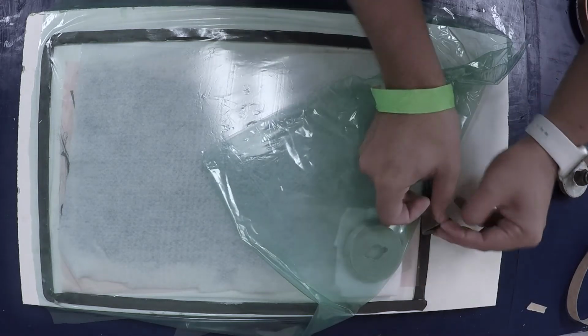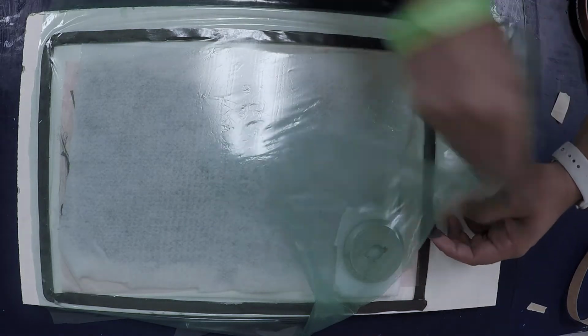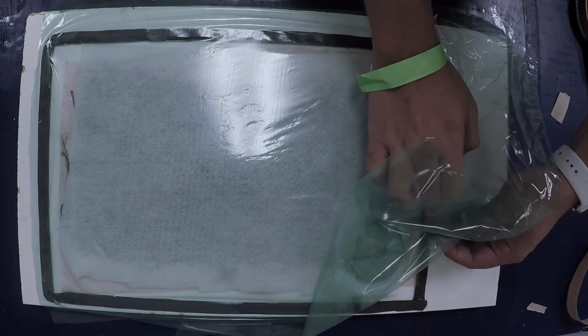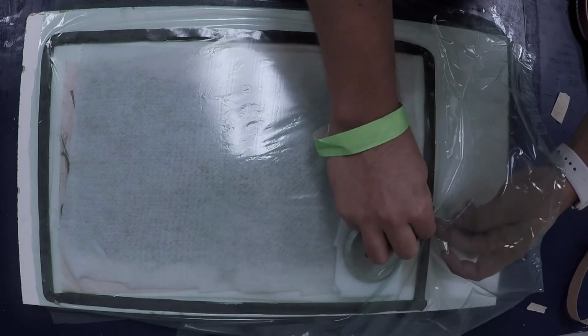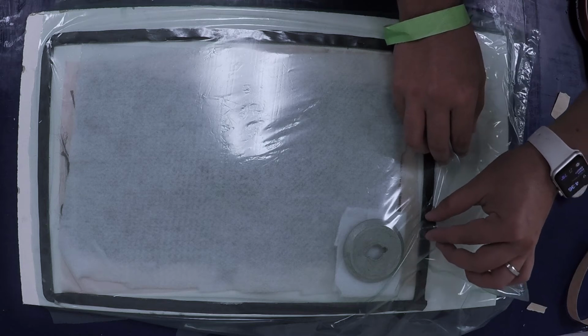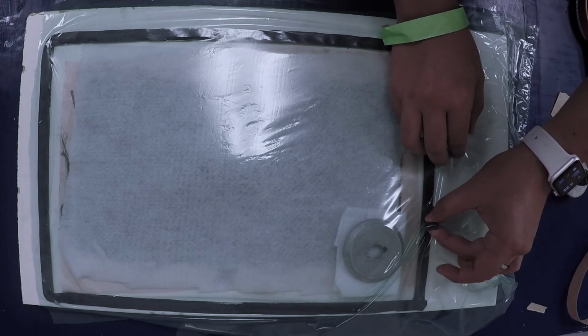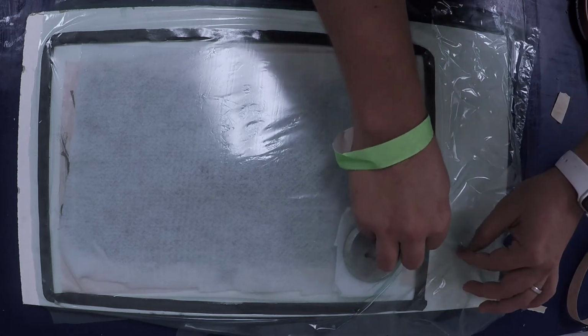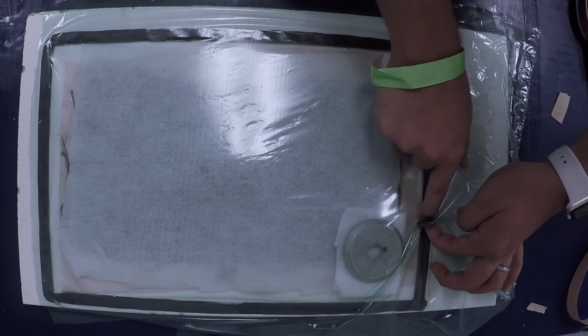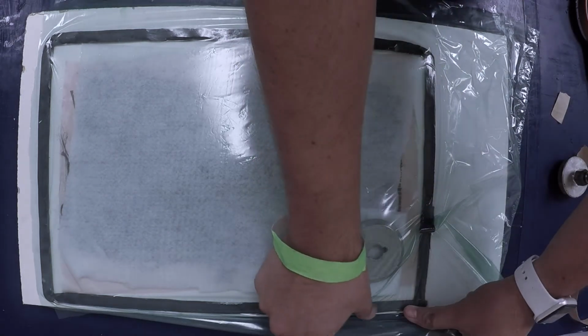As the bag travels around the tape, the excess bag is consumed, which allows you to seal the mold. This technique can be used unintentionally, as shown here, or strategically when performing complex shapes. By adding pleats around the mold, extra bag is allowed to remain over the center, which will be used to adapt to the geometric changes.